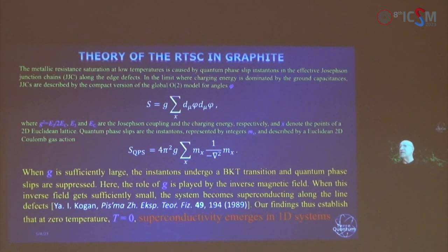Then we can continue with this consideration and show indeed, as soon as we have a connection between superconducting granules along the ring strong enough, we immediately see superconductivity which forms because of the instantons, the resistance because of the phase slips that may destroy superconductivity in a one-dimensional system. Basically, this consideration was first given by Yakov Kogan in his old classical paper, and then we come to the conclusion that at zero temperature, superconductivity emerges in these one-dimensional systems associated with our wrinkles.